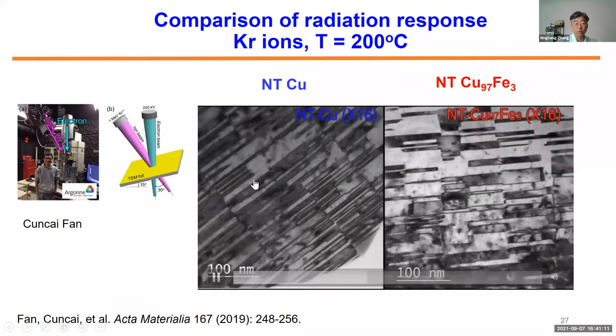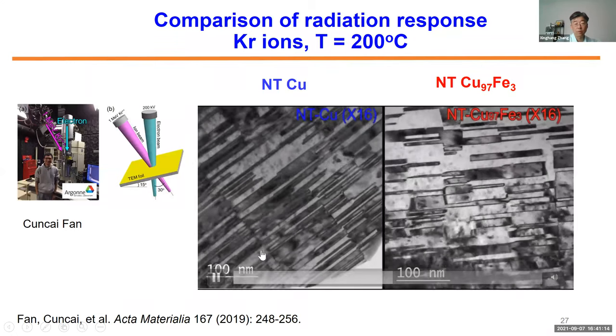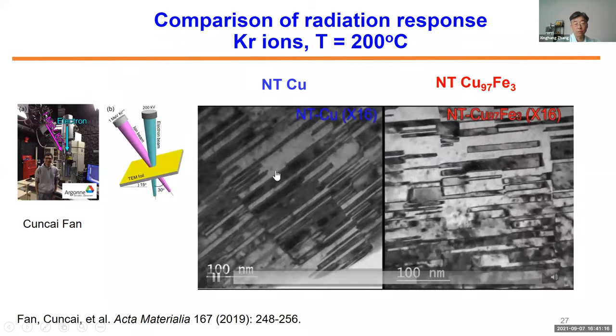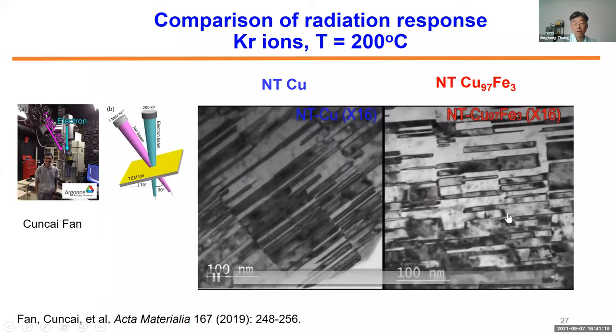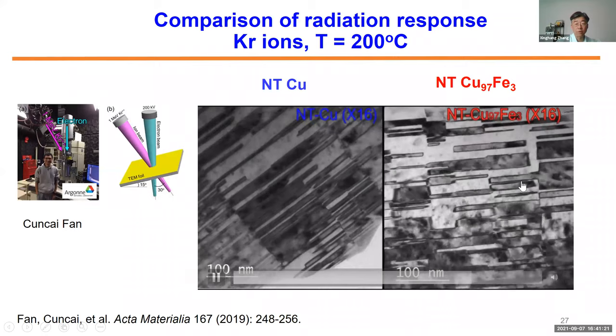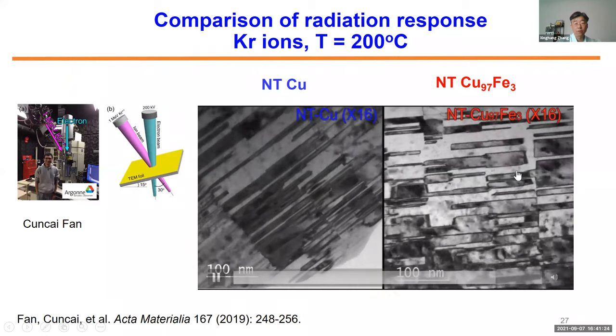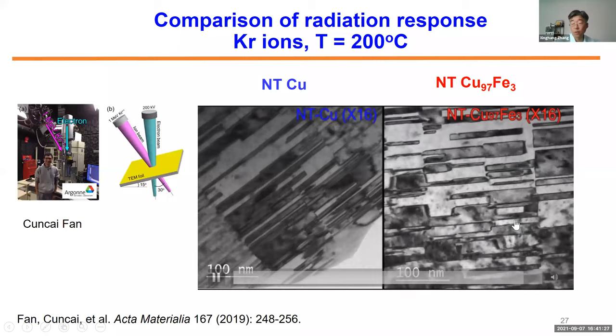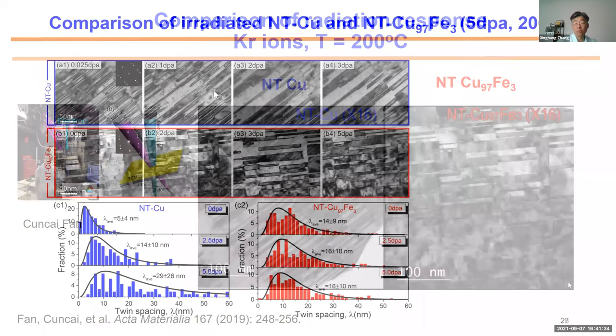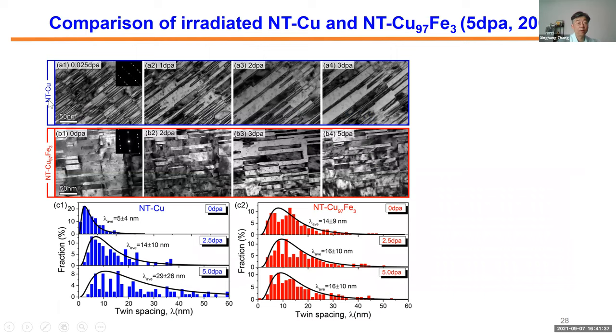All these twins are getting shorter and shorter. And some of the column boundaries now disappear. So this become very large twins. But on the other hand, for this copper iron, you don't see much detwinning event going on. So indicating this idea, maybe it is working. And that is somehow if you dope copper with iron, you can stabilize this twin boundary. So here is a snapshot to show nanotwinned copper after radiation for a while, 3 dpa, and twin boundary disappeared. A lot of twin boundary disappeared. So this is what you have before and after.